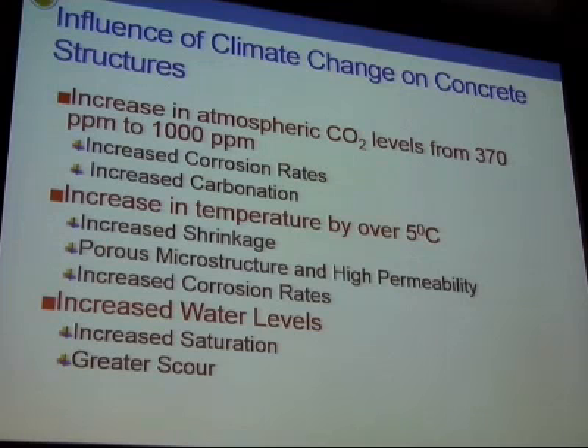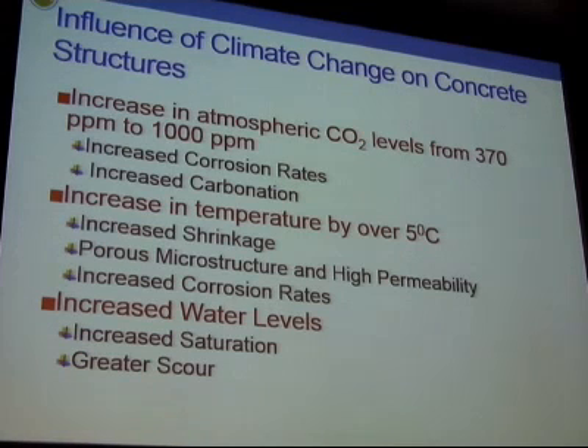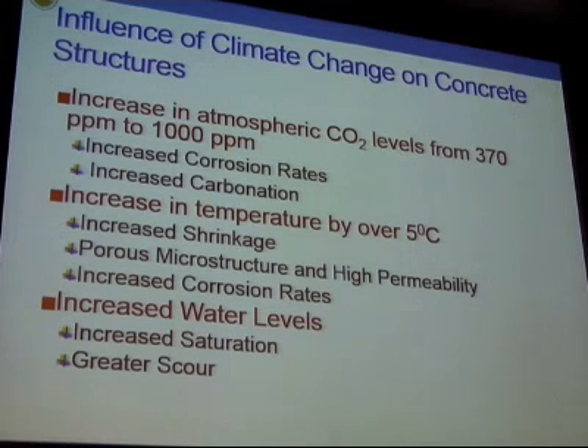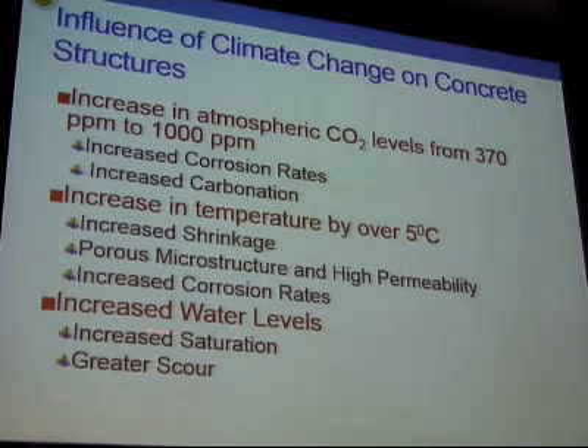Increase the temperatures by over 5 degrees Celsius. It will increase the shrinkage in materials, porous microstructure and permeability, and it will increase the corrosion rates further. Increased water levels give you increased saturation, and you'll get greater scour, which means that you have foundation issues now with higher saturation and higher water levels. So some of the modeling that we have done indicates that in some cities like Bombay or Shanghai, the corrosion can actually start about 9 years sooner if you have this full-blown global climate change in the structure, which means that you also have another issue now to deal with, which is global climate change.